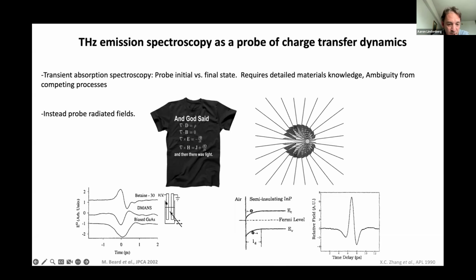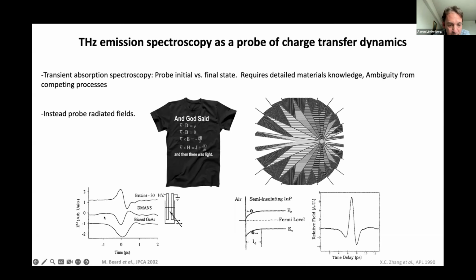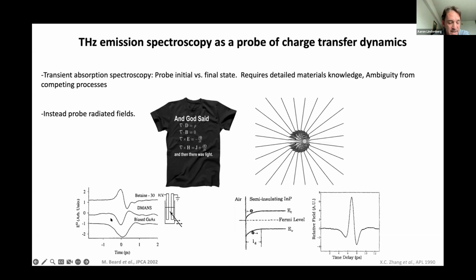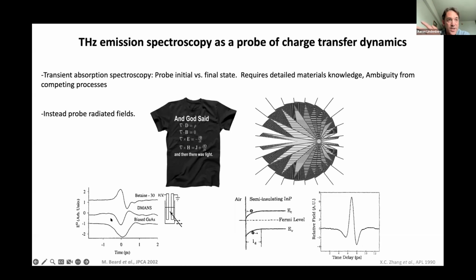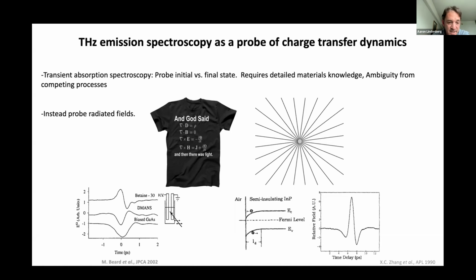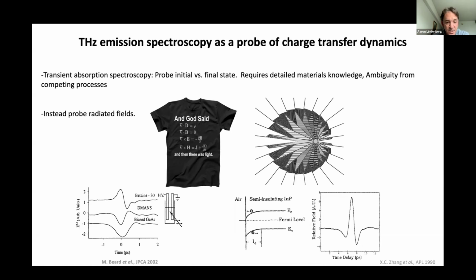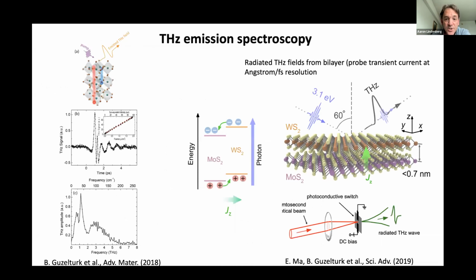Another example, these are pioneering experiments from Matt Beard's group in various chemical systems, probing charge transfer processes within molecular systems in solution and things like that. Okay, so we've been thinking about this for a while. We've applied this approach, for example, to the hybrid perovskites, where you can actually see, separate from the charge motion, indications of lattice modes and really get information directly about electron-phonon coupling. I won't talk about that here.